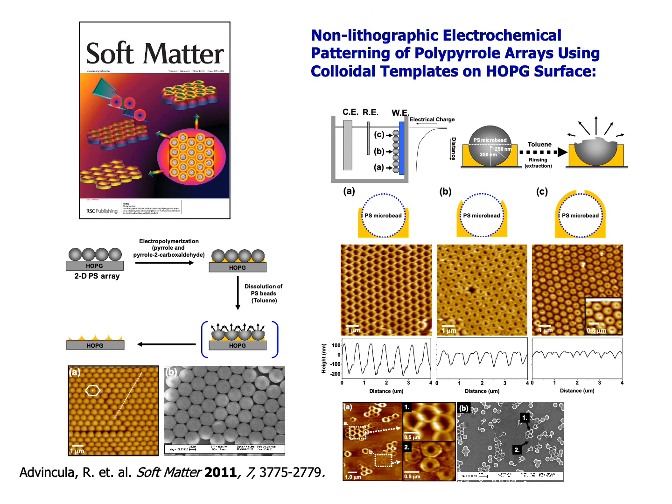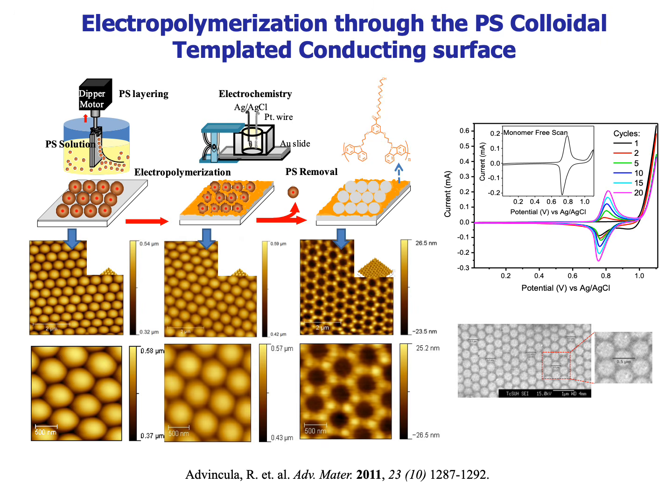So the arrays can definitely be used for electropolymerizing and depositing and patterning polythiophene, polypyrroles, polycarbazoles. In this case, we can take this bifunctional polycarbazole and deposit them on the surface, resulting in a pattern where removal of the conducting polymer results in a beehive-like structure as shown here. So this is an electrochemically deposited conducting polycarbazole on the surface of ITO or gold.